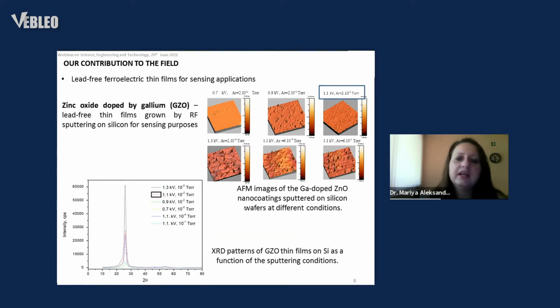As you can see here, these are the atomic force microscopic images of the coatings produced from these materials at the different combinations of growing conditions. They are characterized with different degrees of roughness, and we should select the smoothest one with relatively low roughness as compared to the other ones, because it will need to contact further electrically with the electrodes, with the electrical contacts serving as extractors for the signal. And in this case, we can see two smooth surfaces characterized with 2.5 nanometers average roughness and 6 nanometers average roughness.